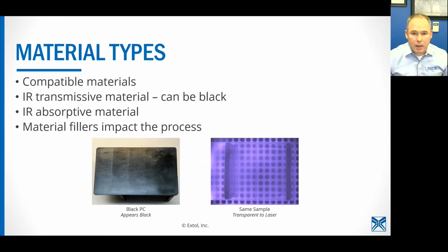Okay, so I've talked a lot about material types, absorptive, transmissive. You've got to have the right compatible materials. We talked about that a little bit. IR transmissive material, as I said, can be black. This is the same part. What you see here is an inspection system where we're illuminating the part with 1 micron light with a 1 micron filter on the camera. So these are the same parts. You can see the weld rib underneath, just as if that top part was completely optically clear.